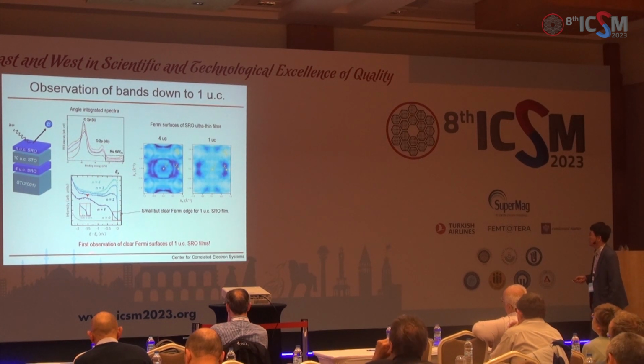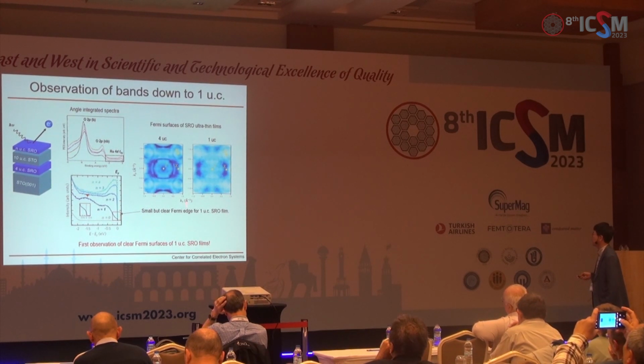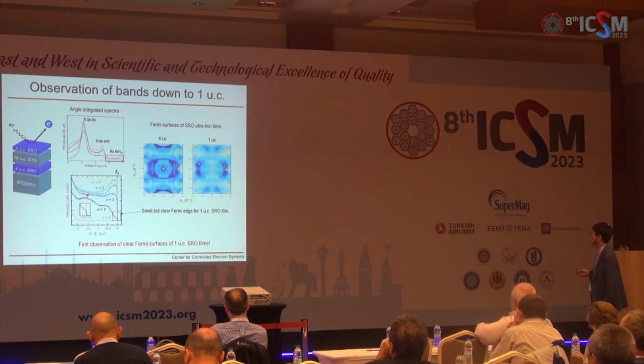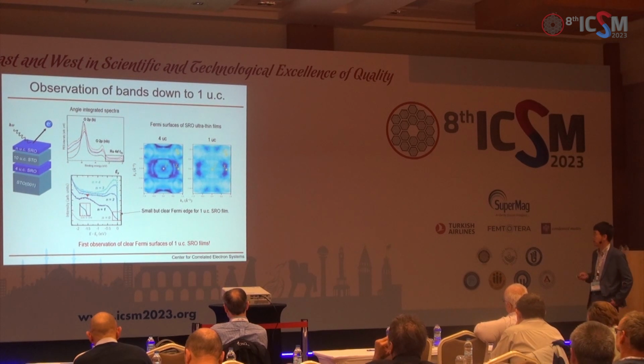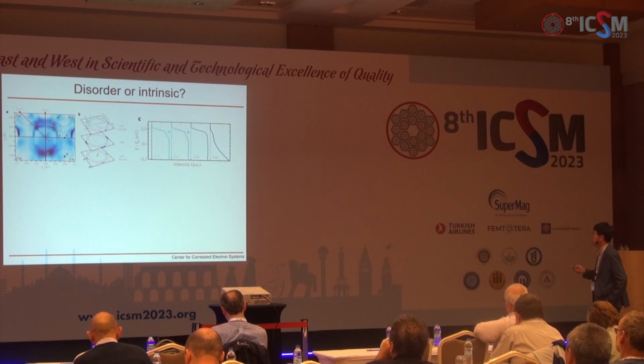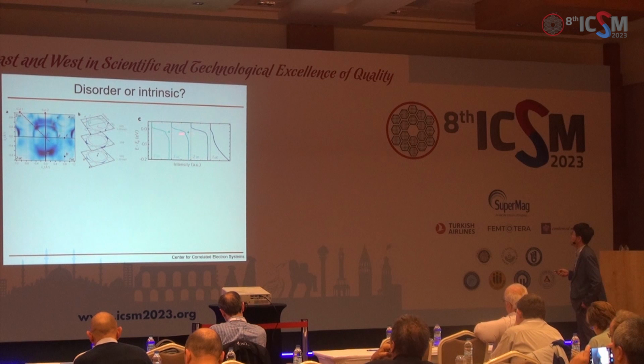So first of all, this is really the first observation of a clear Fermi surface of a 1-unit-cell SRO film. The 4-unit-cell Fermi surfaces are very clear. For 1 unit cell, we still have this spectral weight. That means one unit cell is still metallic in terms of spectroscopy. So let's look at this film thickness dependence.